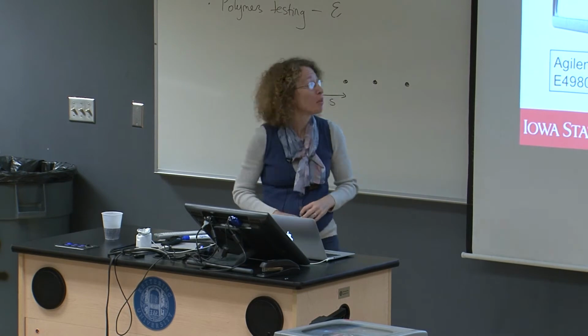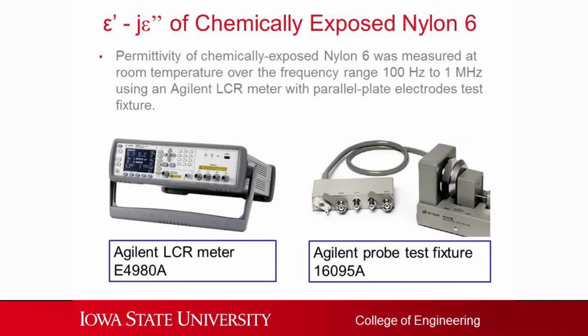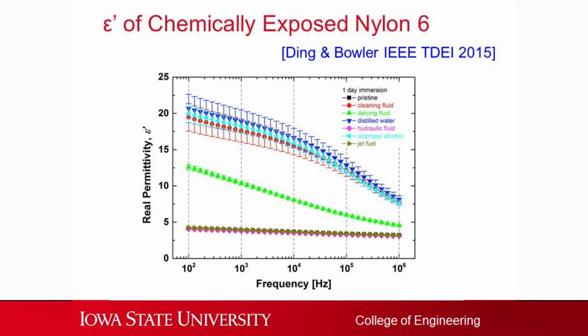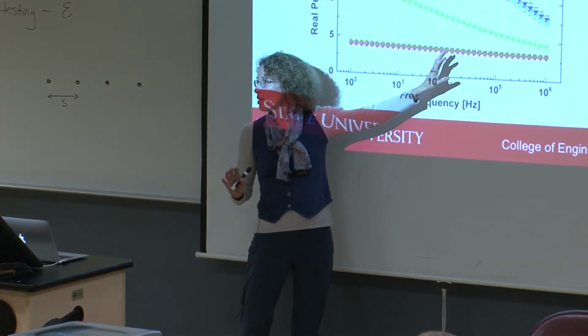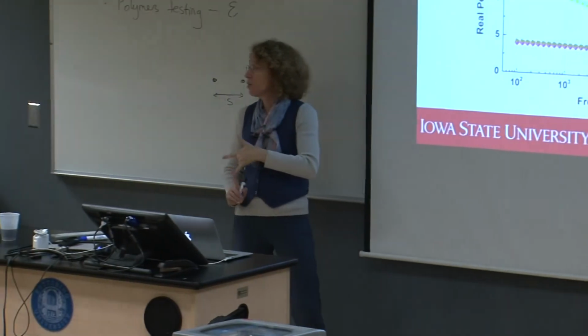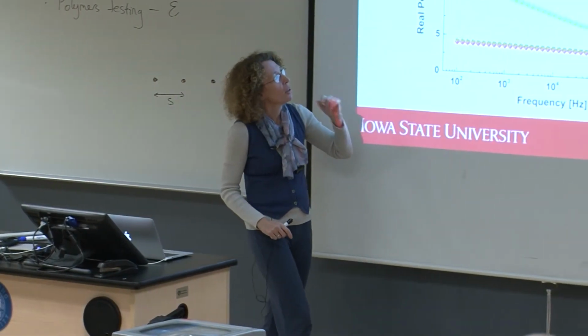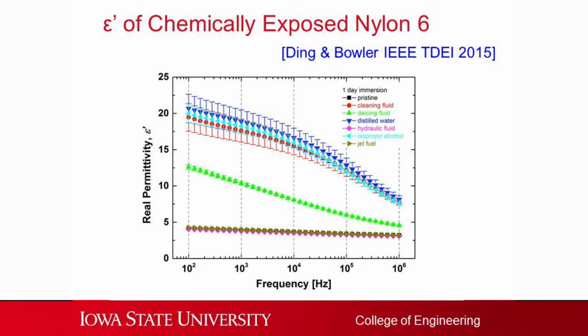So that was the next thing to do. So this is our parallel plate capacitor right here. We can put our sheet-like samples in between those capacitor plates, and then we use the LCR meter to measure capacitance. So as we do that, these are the same colors as before, I think. Underneath there is the pristine material that we did nothing to at all. And as you can see, there's hardly any change when you put them into the hydrocarbon-based fluids, jet fuel and hydraulic fluid. But with those others, there's quite a big change in the permittivity when you've immersed them in water-based fluids.